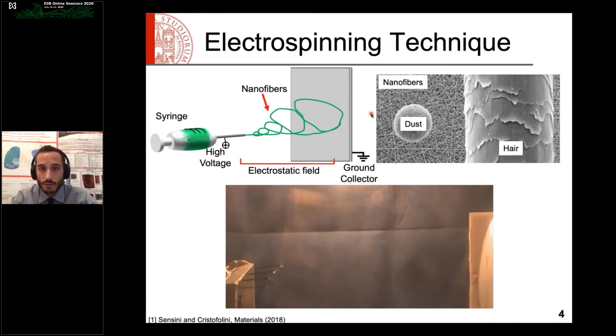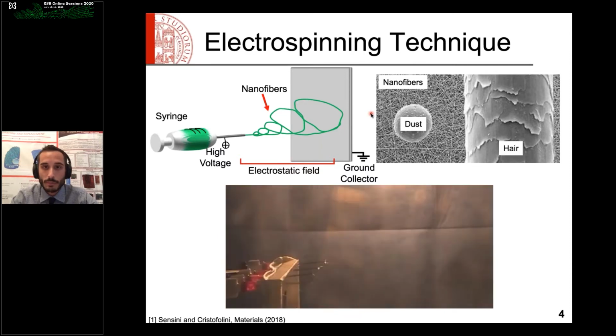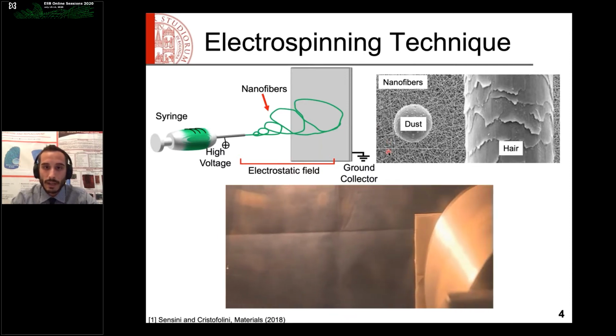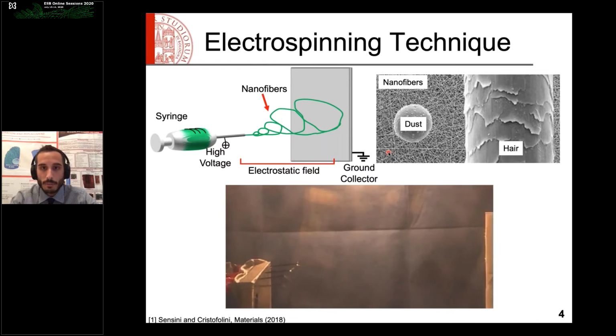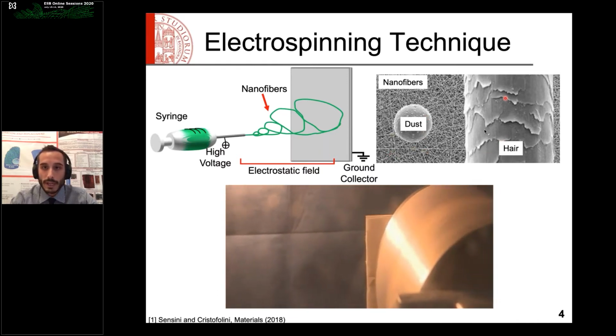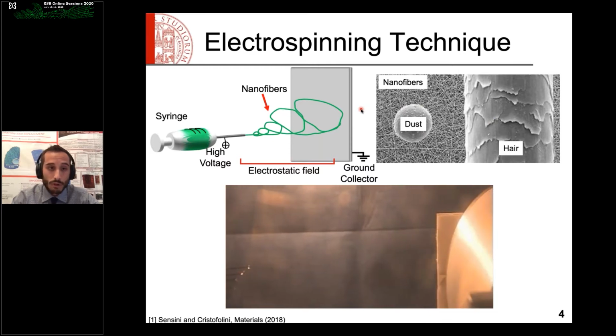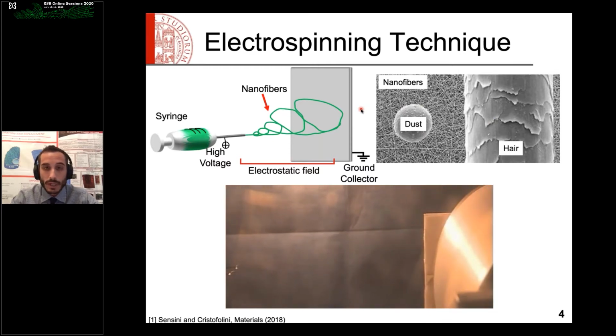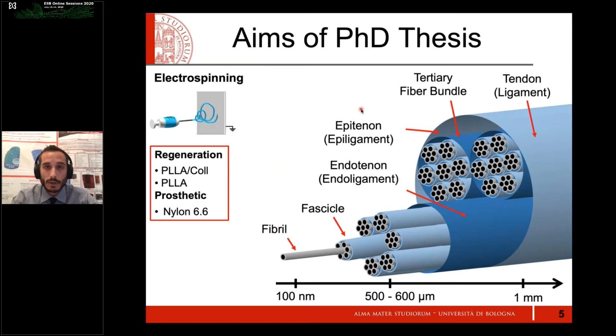Just to have an idea, I show you this scanning electron microscopy image in which you can see in the background a mat of randomly arranged nanofibers compared with a grain of dust and a piece of hair. So taking into account this background, the main aim of my thesis was firstly, using the electrospinning technique, to optimize different polymeric solutions: from the regenerative point of view, blends of polylactic acid and collagen and pure PLA, or for the prosthetic approach, nylon 6,6.